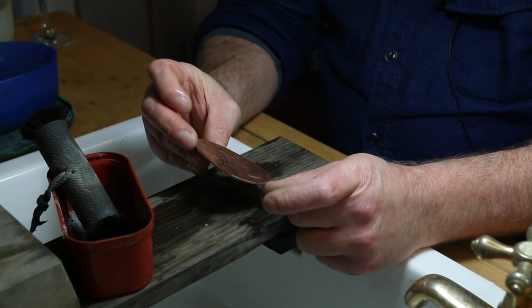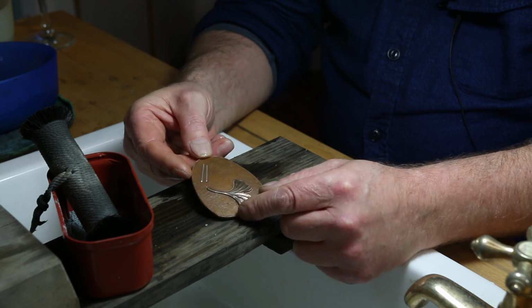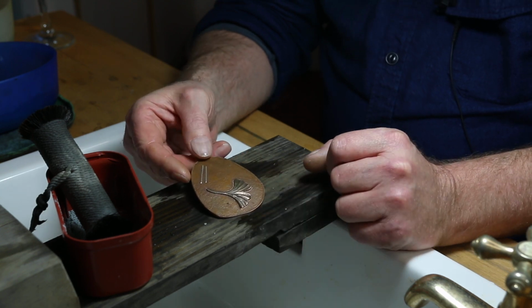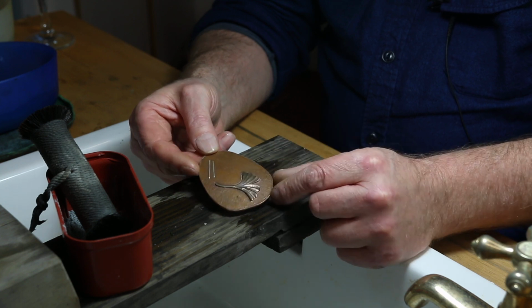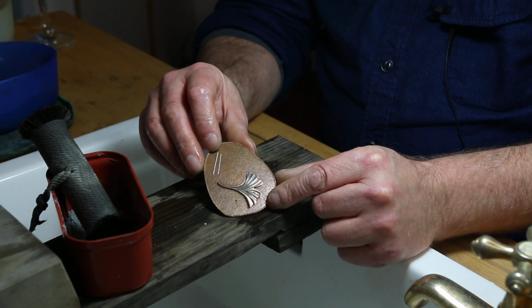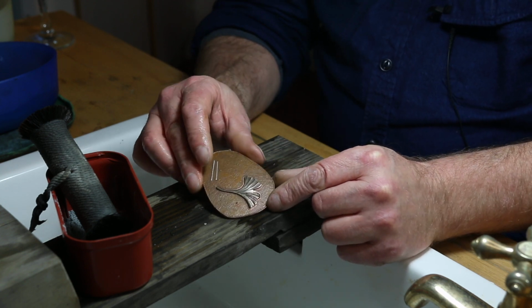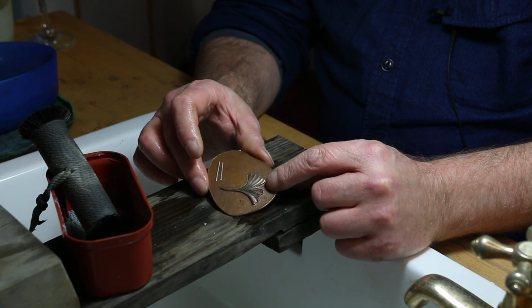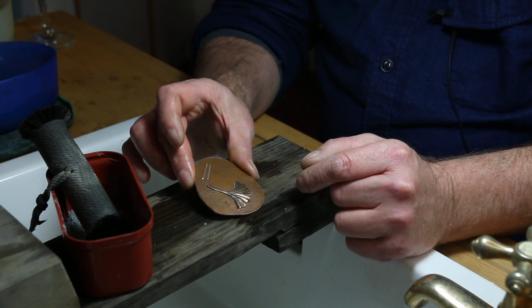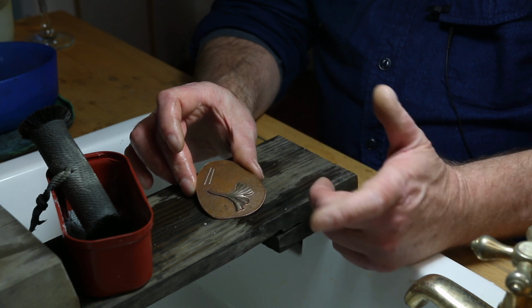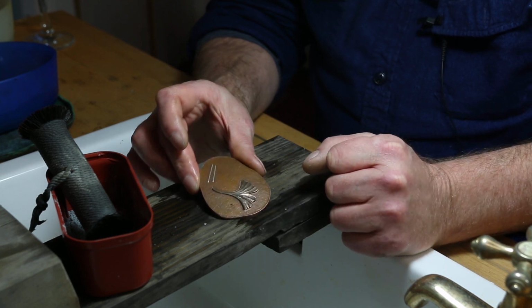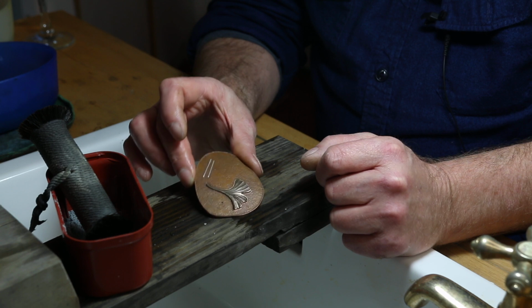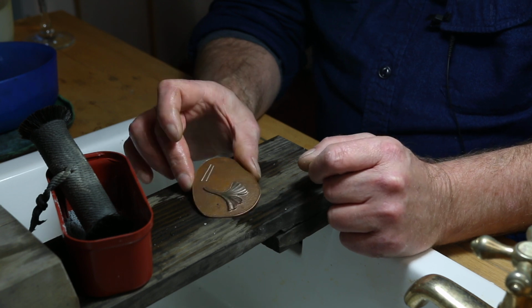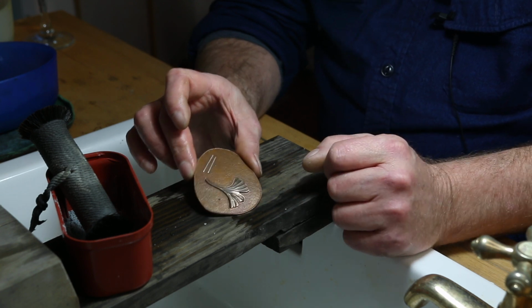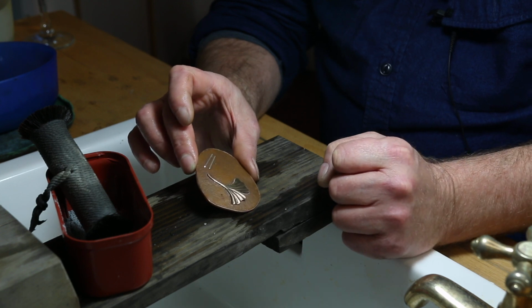Now what we have here is, as I say, a piece that was used as a class sample. It's quite dirty and mucky. There's a reason I chose that one. I'm going to clean this, and I'm not going to clean it very well. And then I'm going to stick it in and let you see the kinds of problems that may occur, if I can make those problems occur, to show you the difference between a poor patina and a really good, solid, rich depth of color.